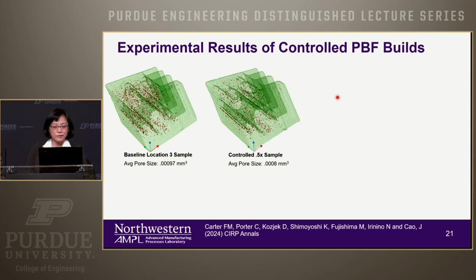So here's the result. On the left is something that we did with the nominal average, everything uniform, and you build it up and you see the porosity. Now, one thing that I want to say is that for this exercise, we use the best known parameters.